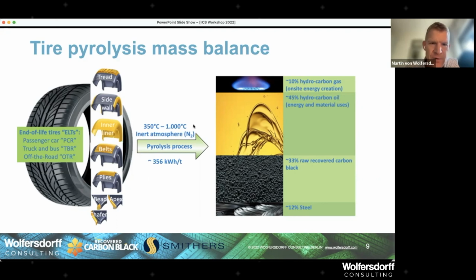So back to temperatures, gasification. I don't see anybody industrializing gasification of tires. I'd be interested how the recovered carbon black looks like. I have a suspicion, and I will tell you in a moment when we talk about recovered carbon black composition. We have an inert atmosphere, which mainly is nitrogen. Some processes, for example, auger processes, need only very little nitrogen. Some other processes, like rotary kilns, need a little bit more because the empty space in the reactor is a little bit bigger. Some processes use steam here as an inert gas, which is also possible.